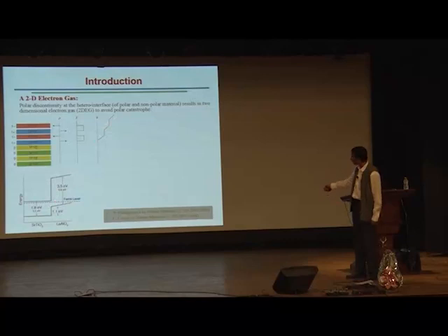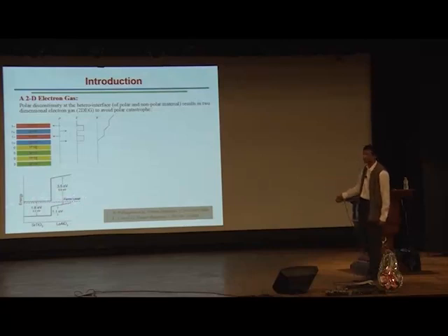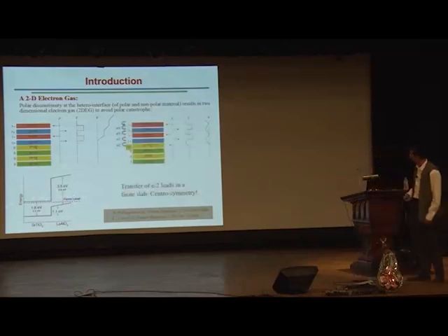Now this potential that's growing up, successive layer of lanthanum aluminate, the top of the valence band is going to bend. So when you reach a critical thickness, this particular energy will cross the energy of the bottom of the conduction band. As soon as that happens, an electron from here, which is occupied, will get transferred into the conduction band of strontium titanate, which is unoccupied, and therefore this charge transfer would take place. What would be the consequence of that?